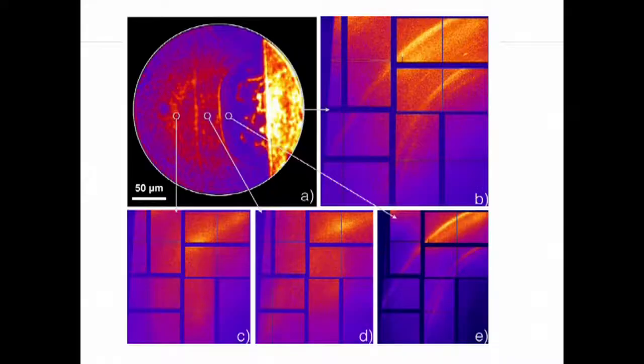Now you can combine this with X-ray diffraction, which we've also done. This is one of the images you saw before, but rotated 90 degrees. Since we have X-rays, we can focus them to different regions in the shock profile and see what state of matter we've created. Initially, before everything, there's not much going on. There are no Bragg peaks, which is normal because we use a single crystal silicon here. If you probe behind the second shock wave, you see diffraction peaks. The Bragg peaks appear that tell you that a phase transition has happened to a shock state of silicon. By evaluating these, you can find out which exact phase transition this is. So this is a technique where you can really combine both: create the high density material, create the shocks, and then evaluate with X-ray diffraction what happens.